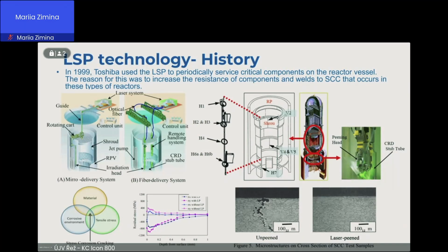in a nuclear vessel. The guru of this technology for nuclear vessels is Professor Yuji Sano. And the method substitutes the tensile stress, which is present after the weld, with compressive residual stress by LSP. Okay.